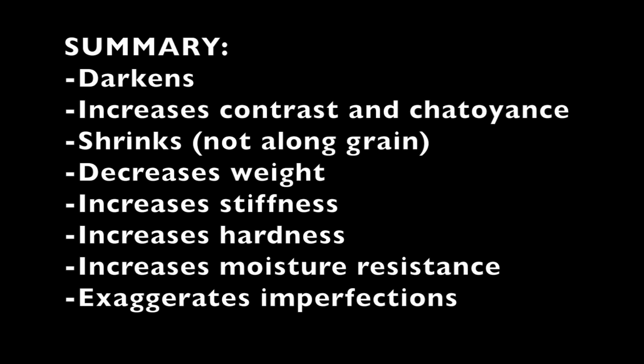Does it increase the contrast and the chatoyance? Yes, it appears to do that as well, as you can see with your own two eyeballs. Does it shrink? Yes, it does shrink a little bit, not so much along the grain, which is to be expected. Does it decrease the weight? Yes, it does. Does it increase the stiffness? Yes, it does.